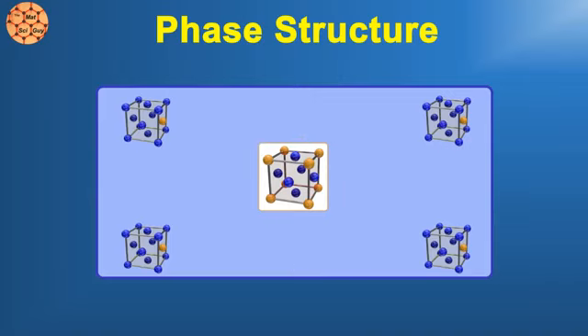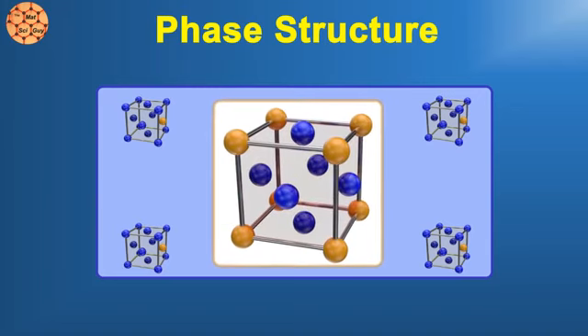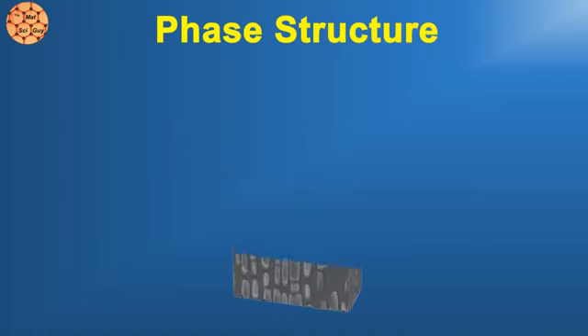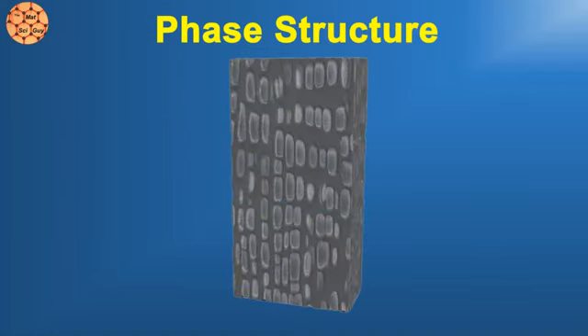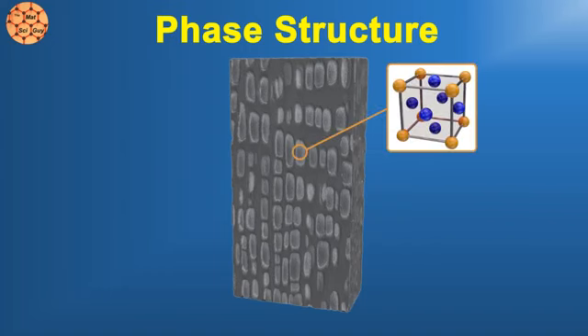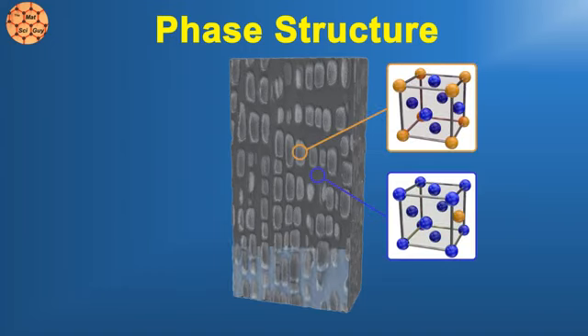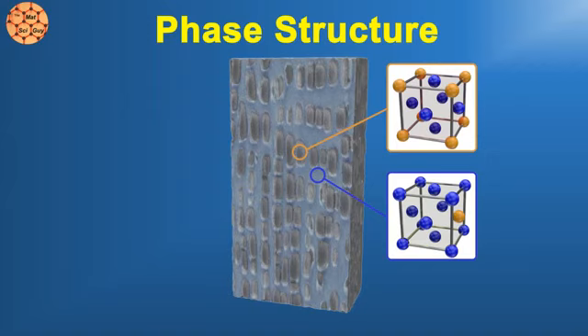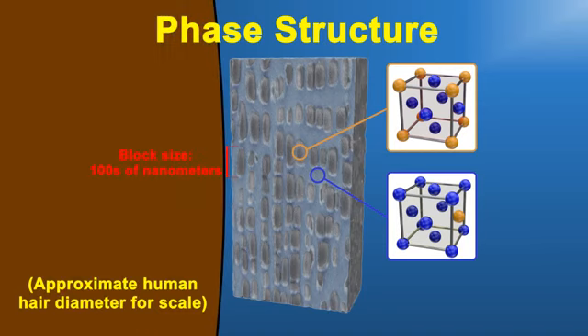In terms of volume fraction, around 70% of the material is made up of this phase. What's amazing is that despite the high percentage, gamma is still the continuous phase. Because of how the solidification kinetics work, a structure is made that is basically gamma prime blocks within a gamma network. Every point of gamma is connected. It's basically like the mortar between bricks, just bricks small enough to fit across the end of your hair several hundred times over.